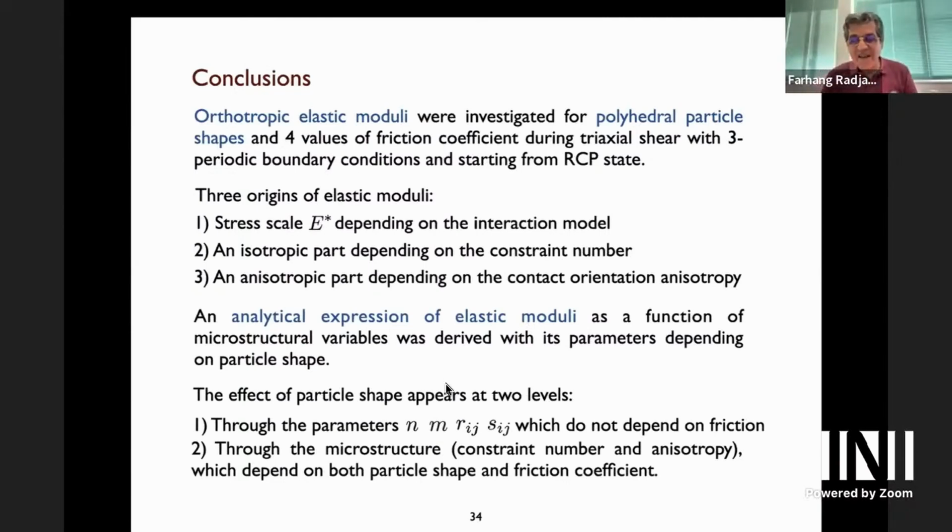Yes. Thank you for mentioning this. That's what makes it difficult. Actually, it takes time because we have to stop the simulation or take a configuration. At that point, we have to wait to relax and then apply the small strain probe. So that's exactly what you are saying. In fact, the stress relaxes during that time. Okay, cool. That's true. And we hope that for this relaxation, the structure doesn't change.